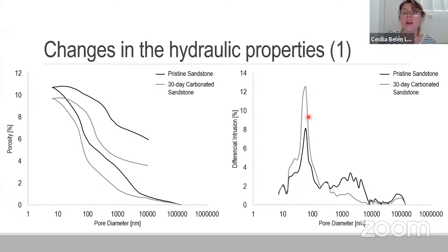On the other hand, we also observed that the pristine sample presented two peaks, or two important groups of pore types: a peak in small pores corresponding to 100 nanometer diameter, and a group of larger pores in the area between 1,000 and 10,000 nanometers.